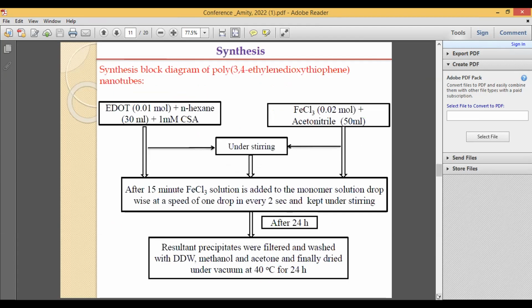So this is the block diagram of the synthesis of PEDOT nanotubes. First we added EDOT, that is the monomer, in n-hexane, and then added 1 millimolar of CSA. In another beaker, we prepared the FeCl3 oxidant in acetonitrile solution. Then they were kept under stirring in different beakers. Then we added the FeCl3 oxidant solution dropwise, at a step of 2 seconds, and kept it under stirring for around 24 hours. Finally, after 24 hours, we collected the product, washed and filtered it, first with double distilled water, then methanol and acetone, and finally dried it for different characterizations.